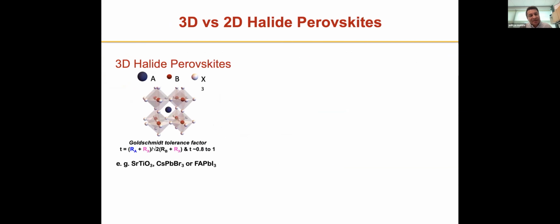So halide perovskites have an ABX3 type structure, and these have been around. For example, strontium titanate is an example of this material. And then of course came the halide perovskites, where the A site was replaced by an organic cation like formamidinium or methylammonium, or it could also be something like cesium. The B site had divalent metals like lead and tin and even germanium in some cases. And then the X site had the halide ion instead of the oxygen, for example, in some of these ceramic-like strontium titanate-like materials.